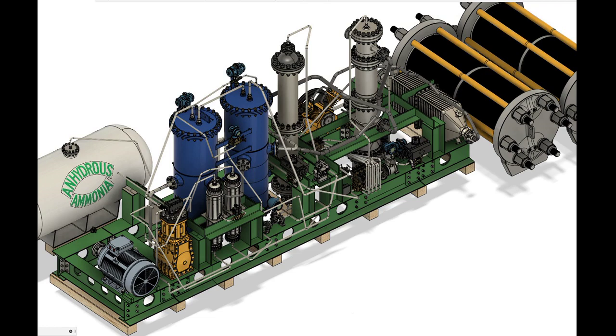While losses from synthesis gas heating can be considerable for a small uninsulated reactor, the fact remains that the preponderance of the energy consumption of ammonia production is not found in the formation of the product, but rather is dominated by hydrogen production, with synthesis gas compression trailing far behind. Over 90% of the total energy consumed in the process is related to producing hydrogen, which accounts for 75% of the volume of the reactant gas, but only 17.8% of its mass.